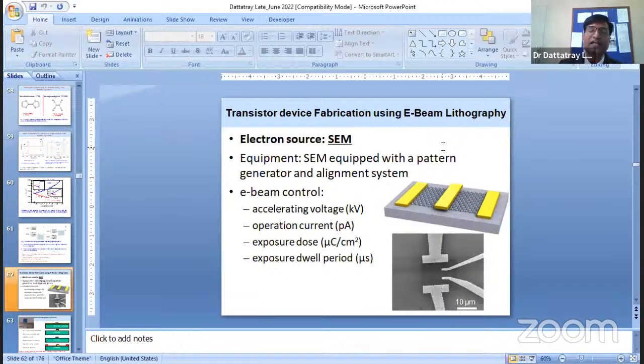Okay, we have done the electronic experiment based on this technology. So what we have done: can we make a technological working device to verify our conclusion that graphene can be more P-type or N-type? And then yes, of course, we have used the electron beam lithography technique to fabricate this kind of device. Again, these are graphene transferred by micromechanical exfoliation onto a Si substrate. We have fabricated the device using electron beam lithography, and these are the devices.